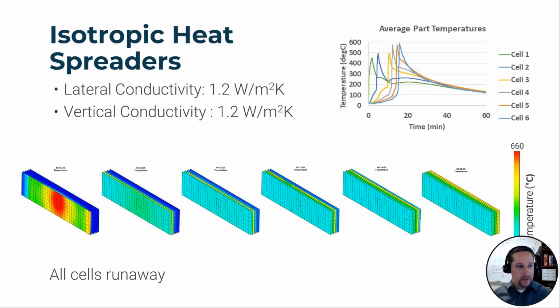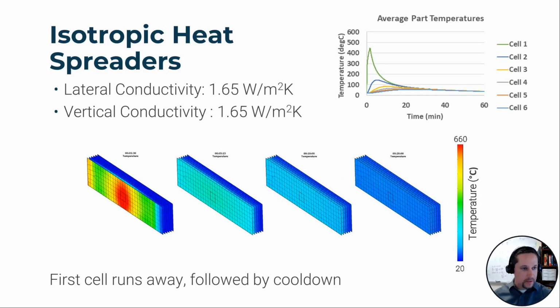If we were to simplify this and just look at isotropic thermal conductivity, this could greatly affect the prediction that we get, and that could also be an important safety factor for the design of vehicles. So in this case, we've taken a common thermal conductivity value of 1.2 watts per meter Kelvin. And what we see when we simplify this heat spreader material properties is that the thermal runaway is predicted to propagate through the entire pack. And that's not really realistic compared to the more accurate case.